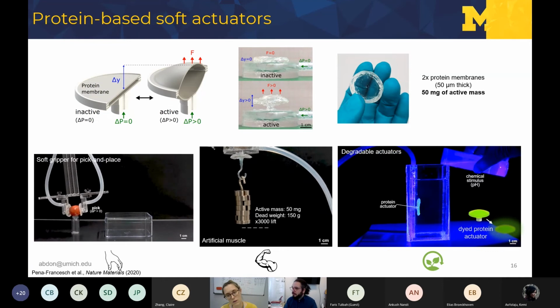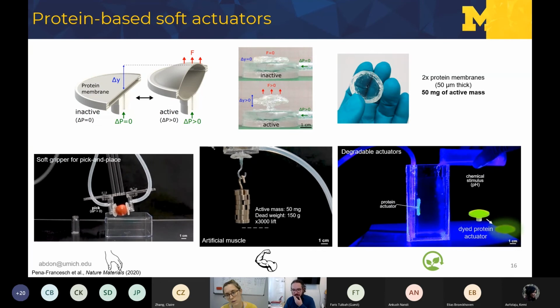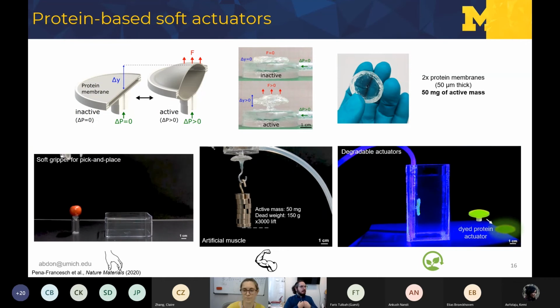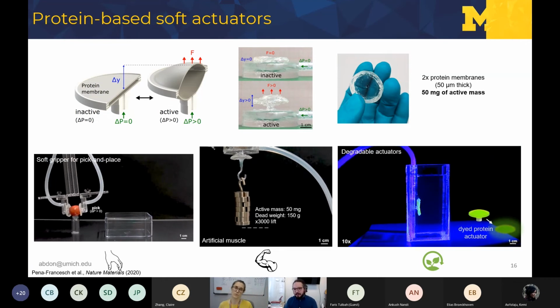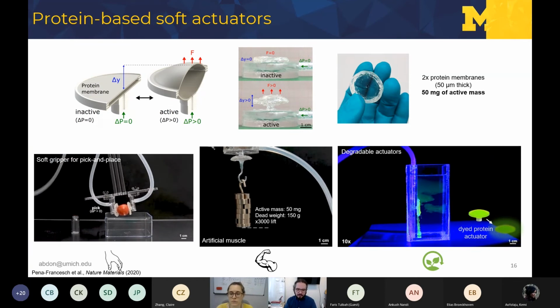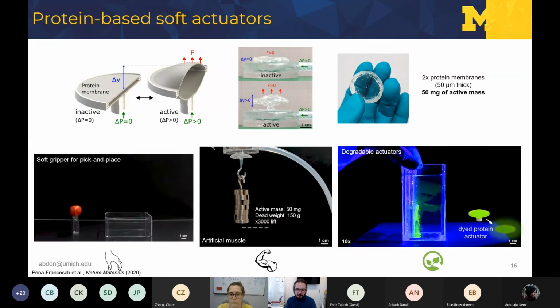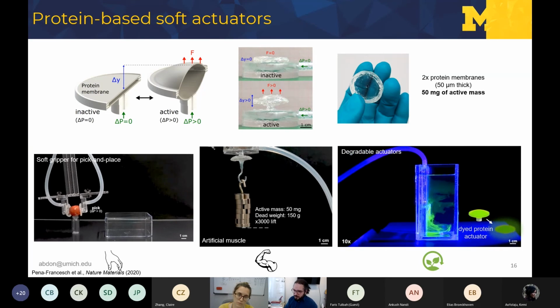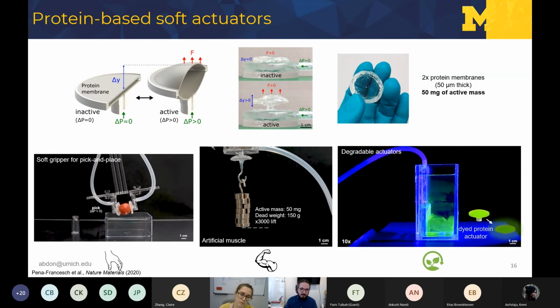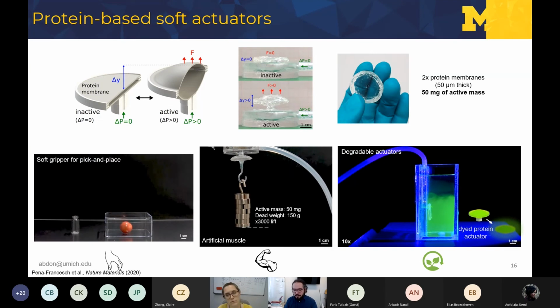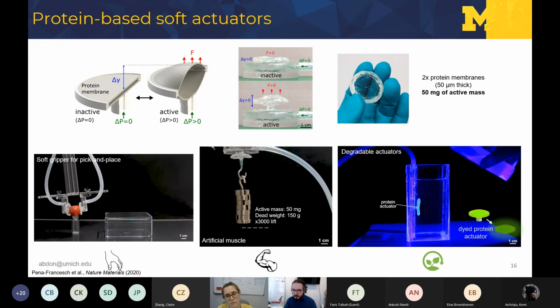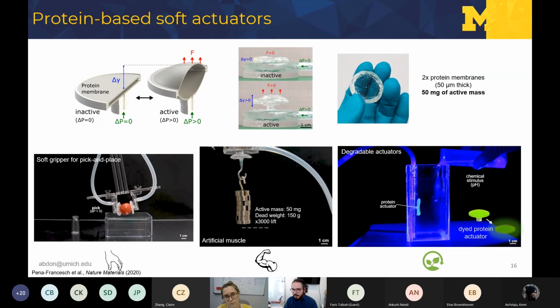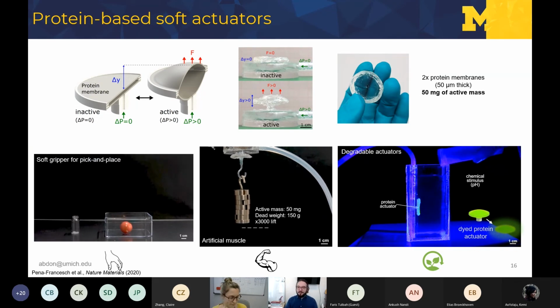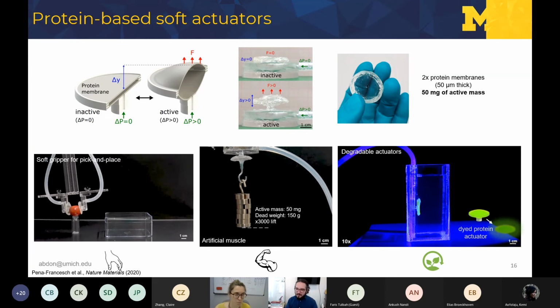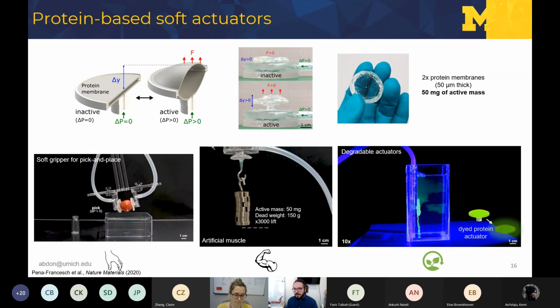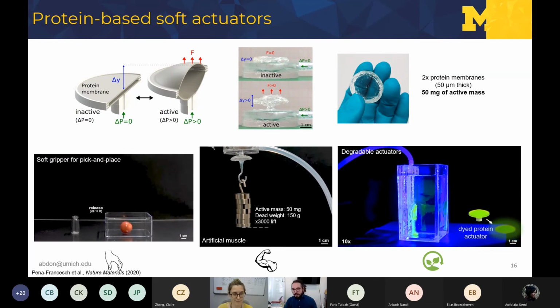and performs quite well. And also, we're very interested in taking advantage of this dynamic cross-linking and this reversible cross-linking, not only from the healing perspective, but also from a sustainability perspective, right? Not only for recycling these materials, but also for enabling the degradation of these actuators, especially with field robotics in mind. So in this case, this is a chemical stimulus. This is pH, which is very fast, and we use pH for a bit of drama and to have a fast video. But of course, this can also be enzymatically degraded, and you can control the degradation kinetics for a desired degradation profile.